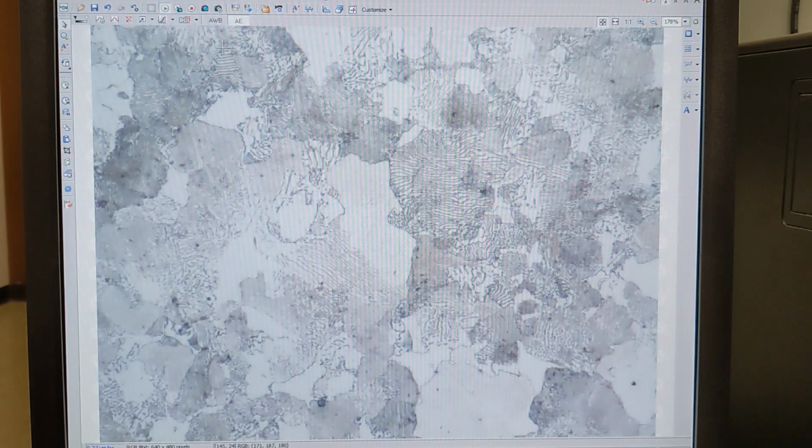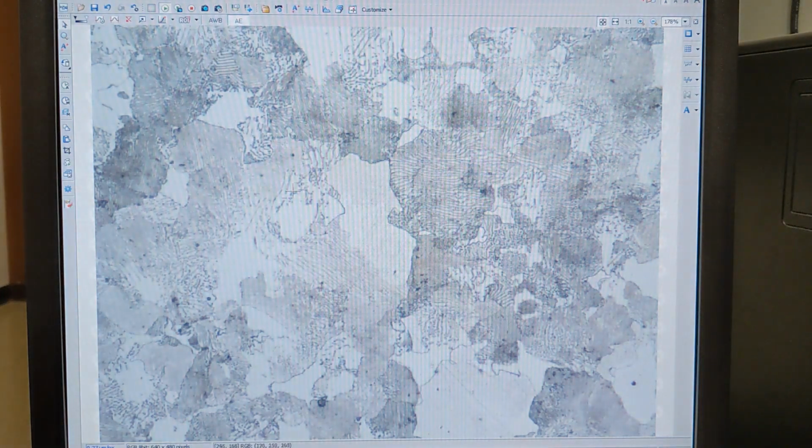And 700 Celsius, it's a little bit higher on the TTT diagram. So this is likely to be our coarse pearlite. And as you look, you can hopefully see we have some definite pearlite layers, layered structure, ferrite and cementite, especially right here.